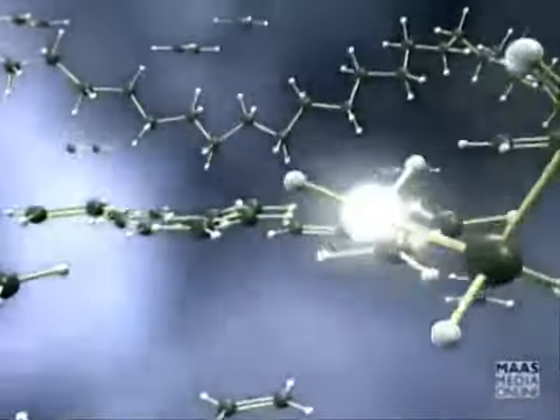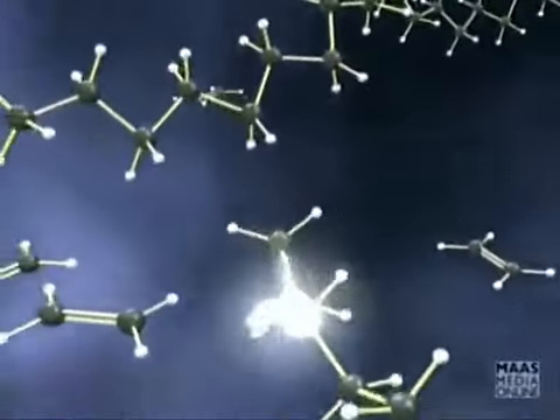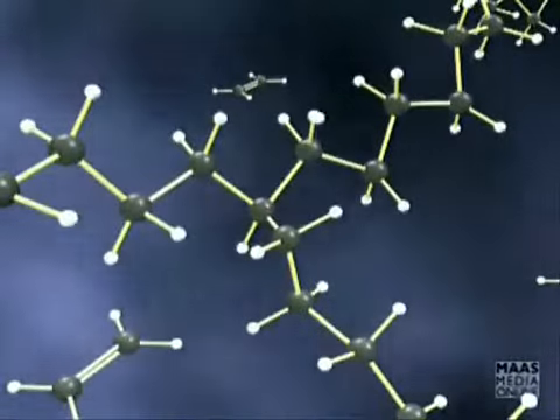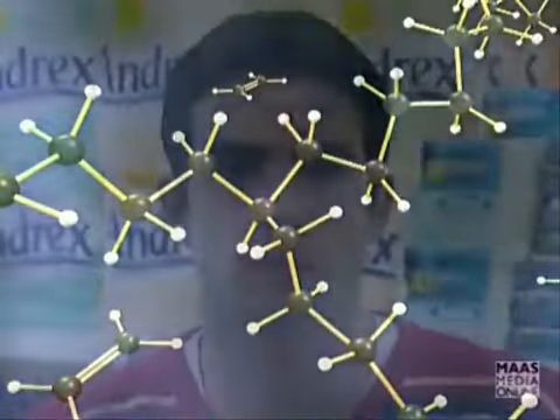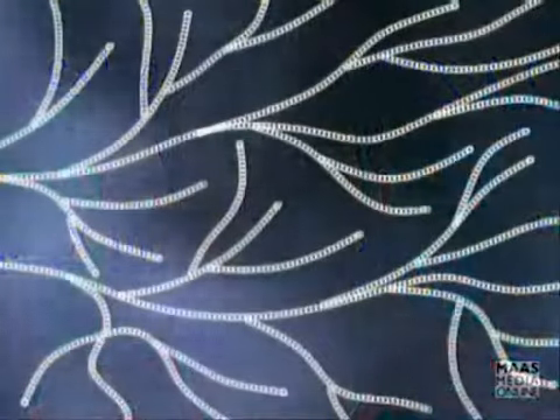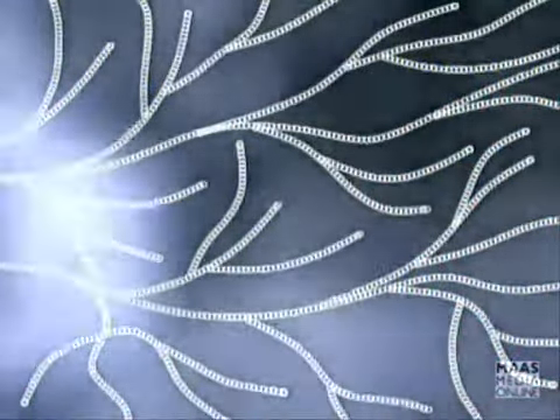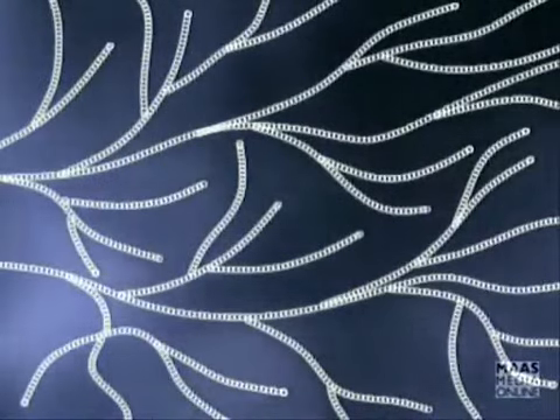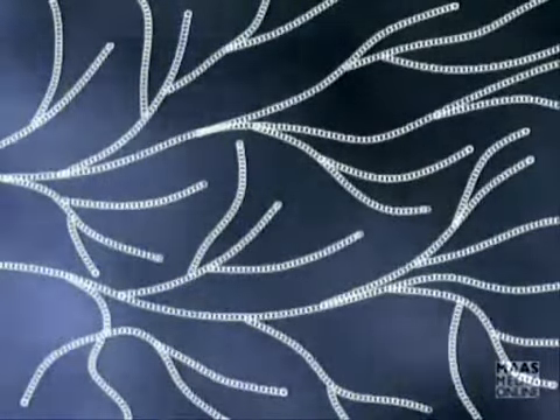But the active end of a growing chain can also break into another chain by displacing one of the hydrogen atoms instead of splitting a carbon double bond. This leads to branched molecules as opposed to perfectly linear chains. And the size, position and frequency of these branches has a serious effect on any crystallites, and therefore affects the properties of the polythene. Low density polythene, LDPE, has random branching of both short and long chains. This irregular structure prevents too many crystallites, and so the polythene is very flexible but tears easily.